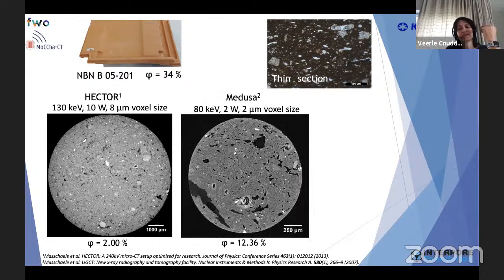If we scan this with our system, for instance with a sample a few millimeters in diameter, at a voxel size of 8 microns, we can only detect a porosity of around 2%. If we take a much smaller sample, around 1 millimeter in diameter, and scan with another system reaching a resolution of 2 microns, we can detect much more pores, around 12% in this case.